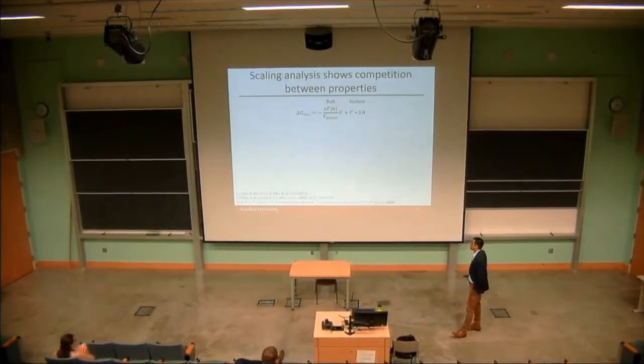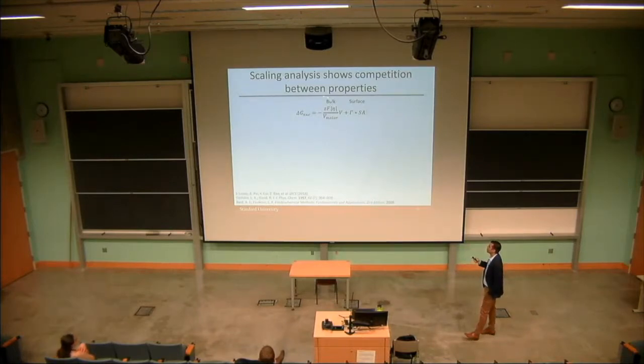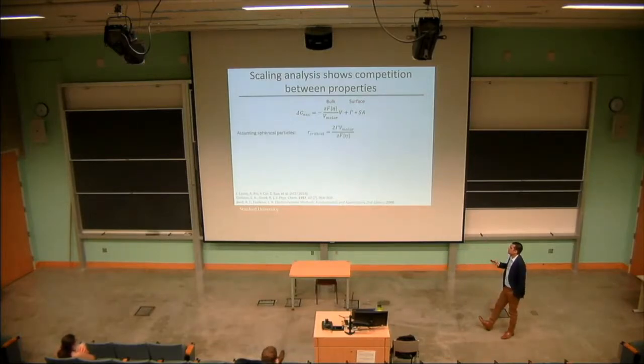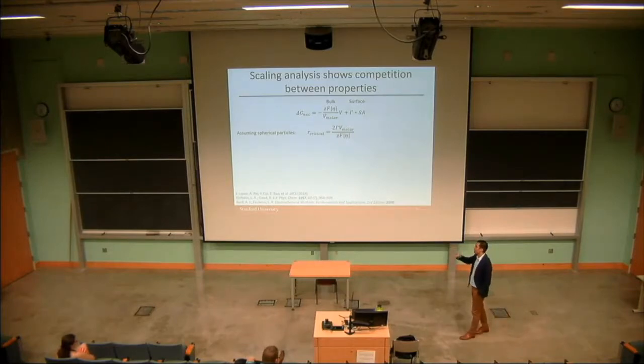So what we turn to is the thermodynamics of the lithium nucleation process. And this is the free energy of nucleation of just any particle electrochemically. It's a balance between the bulk effects, which are driven by the overpotential of the process, and then the surface effects, which is just governed by the interfacial energy times the surface area. And so you can differentiate this and assume a spherical particle, and that gives you a critical radius of nuclei. So below this, nuclei won't form, and it'll just go back into solution. But above this, you will have a nuclei form and deposit on the surface.